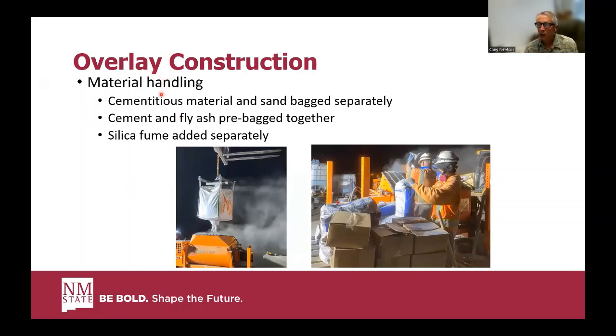In terms of material handling on the job site, we required that the cementitious materials be bagged and the aggregate, sand, bagged separately. So the cement and fly ash were the cementitious materials that were stacked. Silica fume was actually used straight from the sacks provided by the manufacturer. And basically what the contractor did was they chose the batch volume so that it would be an even number of silica fume sacks. Everything worked well on the mixers. They basically set the mixers up at one end of the job site and then placed concrete from the far end toward the mixers as the pour progressed.